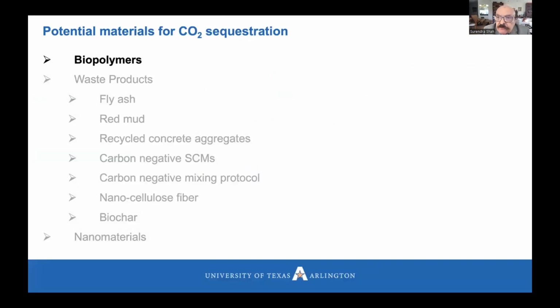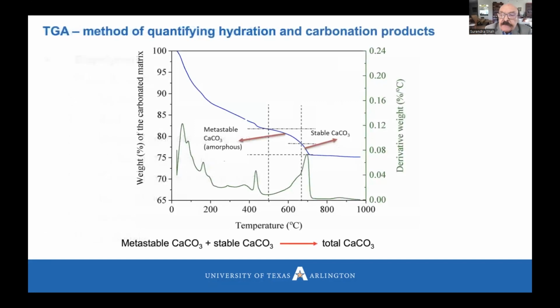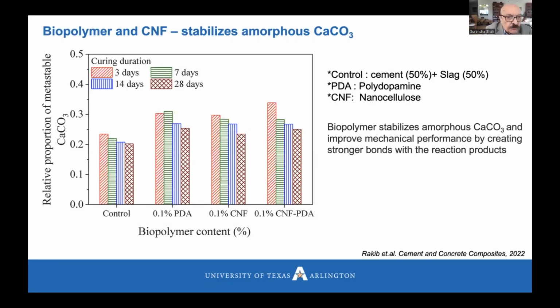So as I mentioned, we can control the morphology of calcium carbonate by biopolymer. And so we did some tests where we carbonated it with additives of biopolymer, and to see how much amorphous calcium carbonate and how much is stable, we use this thermogravimetric analysis. And from this analysis, the results are shown here.